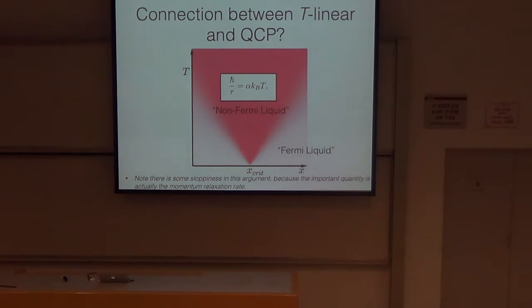Now, there is some sloppiness to this argument, and it's related to a question of Phil's to Subir yesterday, which was, well, do we know that the scattering rate is exactly going to be what we see in the resistivity? Because, of course, what we measure in resistivity is the momentum relaxation rate, and not necessarily the quasi-particle lifetime, which are not always the same thing. But nevertheless, ignoring that fact just for now, the basic idea has often been to associate the observation of T-linear resistivity with the presence of an underlying critical point.